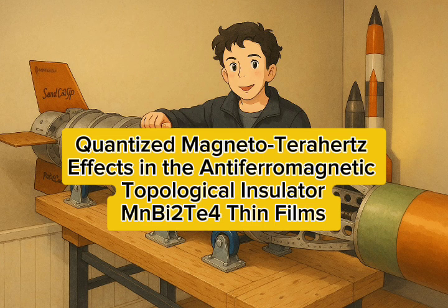They used terahertz light. Yes, terahertz spectroscopy, or THz spec. And there's a good reason for that. That energy gap I mentioned, the one that opens up on the surface of magnetic MBT, its size is right in the terahertz frequency range. So terahertz light has just the right energy to see that gap and probe those topological states. Perfectly put. It's the ideal tool. Remember, terahertz is very low energy light, much lower than visible light.